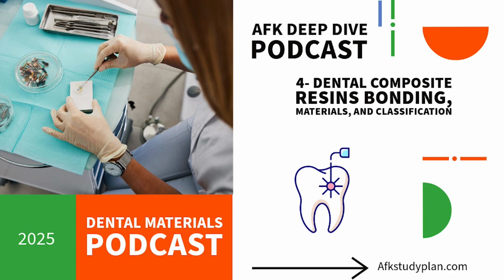How long do you cure for? It depends on the material and the light, but the PDF mentioned around 40 seconds for a typical 2mm layer is common. Light cure is also generally less prone to that oxygen inhibition issue on the surface. Sounds much better. Any downsides to light cure? Well, the light only penetrates so deep. So for fillings thicker than about 2 or 3 millimeters, you have to place the composite in increments, in layers, curing each layer before adding the next. Layering. That can take time for big fillings.